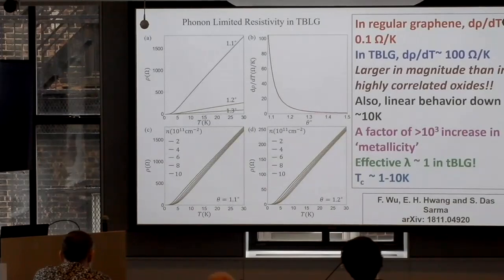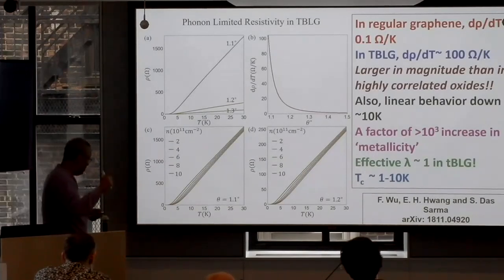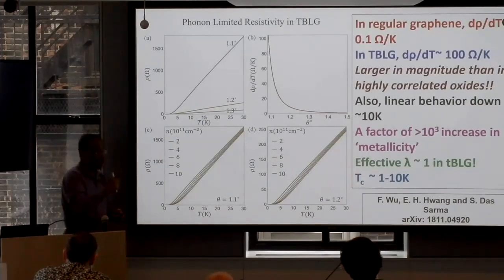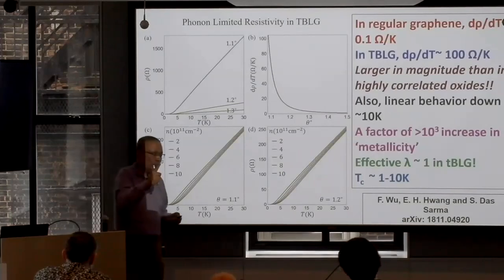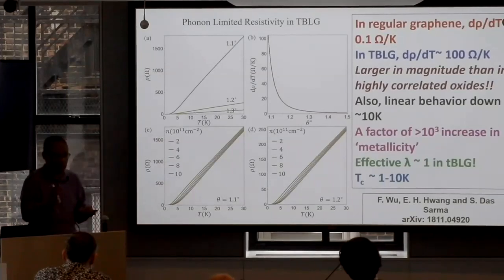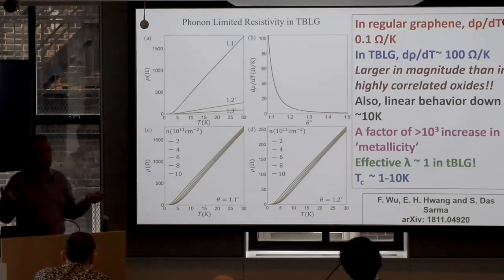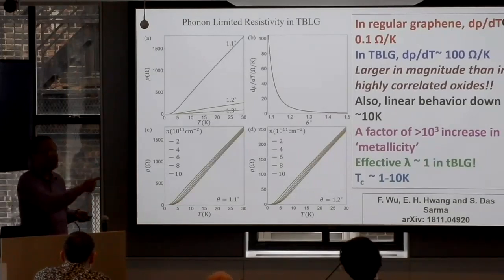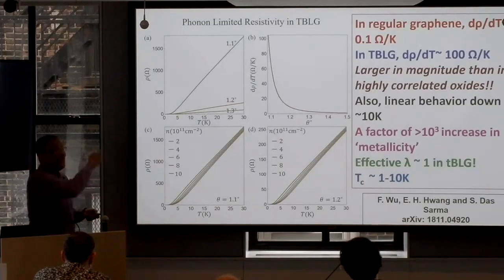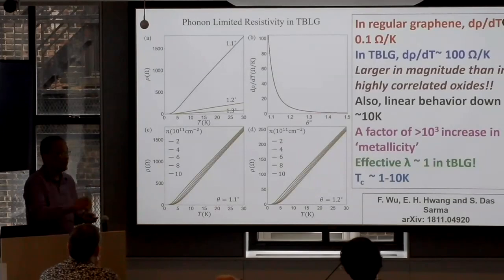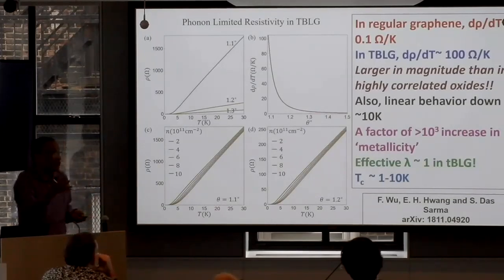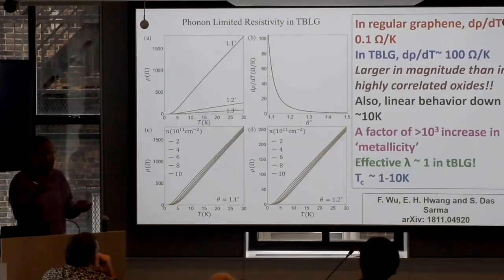Electron phonon coupling goes up in the simple theory because a velocity comes in the bottom. You bring up a very good point. The basic deformation potential coupling D most likely changes. And I'll come to that when I talk about superconductivity. Because I don't know if you know, this deformation potential coupling, which basically means if you apply pressure, how much the bands change, it's not known even for a material like silicon or gallium arsenide very well. So it's often set by comparing with transport experiments. And answering the question, we do need a larger value of D than what it is for monolayer graphene. And this is the open question. Some first principles person here perhaps can do this calculation. And referees bring up this question, and it's a justified question, but I'm talking about it.